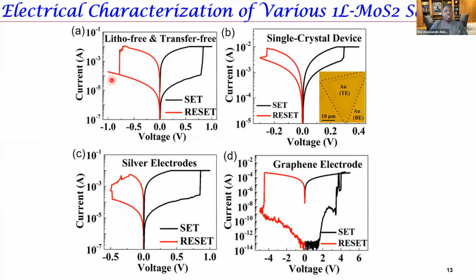So as part of the criticism we received, we went through great effort to make very clean samples. As all of you who do experiments know, when you make samples with lithography, you have contamination, and those contaminants could play a role - that's a very fair argument. So we said, let's make very clean samples. These are what we call lithography-free, transfer-free, going back to the question David mentioned. So these are MoS2 materials that can be grown directly on gold foil.